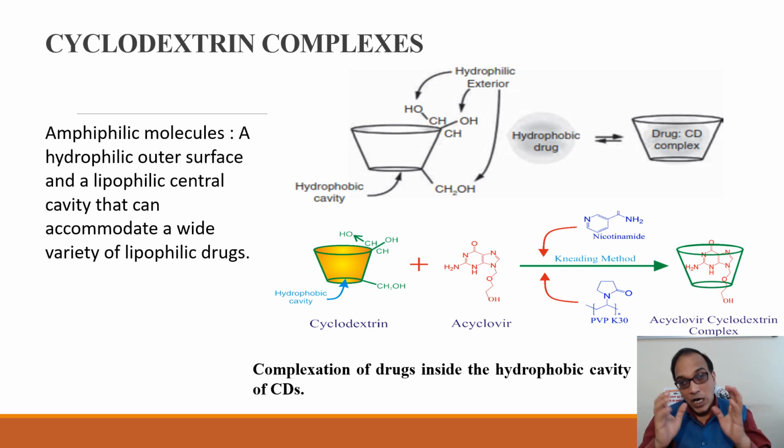It has a hydrophilic exterior and a hydrophobic cavity. So the drug goes inside with or without any hydrophilic excipient. Like in the case of acyclovir, we have used nicotinamide and PVP as hydrophilic excipients. With the kneading method, we prepare the acyclovir cyclodextrin complexes.